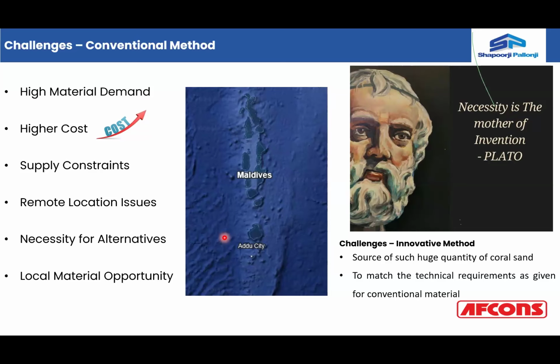And because in that particular road, we have a CTB layer, the cement treated base layer, we try to use the coral sands in the CTB. As you rightly pointed out, necessity is the mother of invention, and this is exactly what went right in this particular case for coral sand. We tried to use it because there is no other option available. We don't have any other option but to try and test the naturally available material for its suitability as far as the contract specification is required.